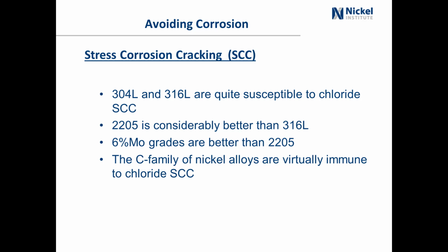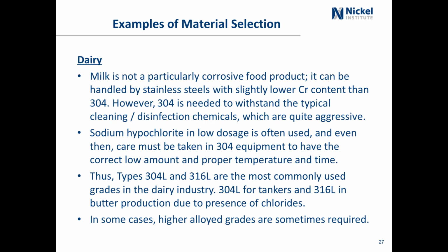6 moly grades are better than 2205. And the C family of nickel alloys, which are like the Hastelloys, which the other fellow was asking about, are virtually immune to chloride stress corrosion cracking. And we can see here, the PREN gives us a clue because as the PREN goes up, resistance to chloride stress corrosion cracking increases. Some examples of material selection.